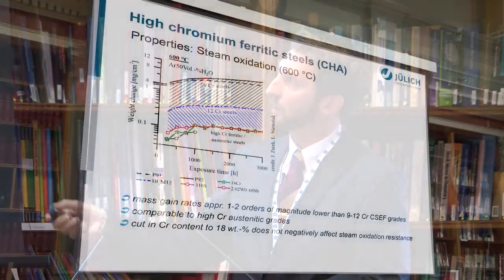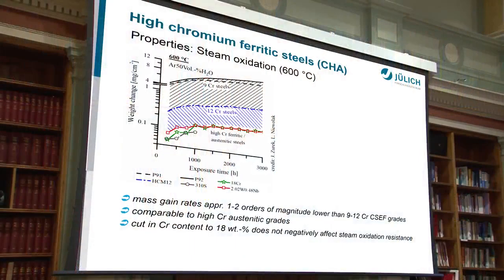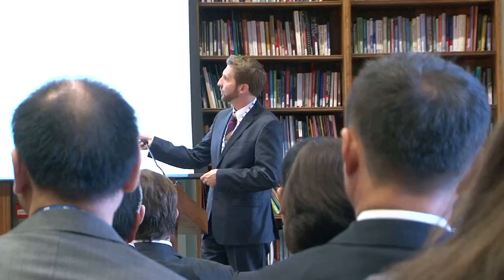By manipulating and optimizing thermal processing, alloy variations which exhibit adequate creep strength at up to 650 degrees centigrade can be achieved. This represents a remarkable breakthrough with this class of ferritic stainless steel. Finally, Bernd outlined an ongoing program for the development of compatible welding electrodes for the advanced variants of the new alloy designs.